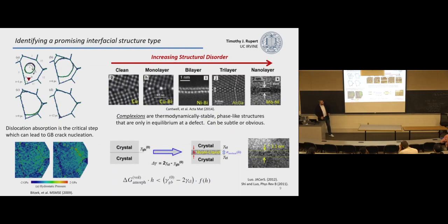And people have developed really nice thermodynamic descriptions of what's happening here. We don't need to dig into it too much because we're just going to go and apply this and make materials with this. But the basic idea is you need to think about the energetics of going from a single grain boundary with an energetic penalty to now 2 crystalline-amorphous interfaces and then some amorphous region at the center. And when this right type of configuration has a lower energy than the left, that's when you're going to form these amorphous grain boundaries. And this is just an example of somebody going and finding one of those that's a little over a nanometer thick.